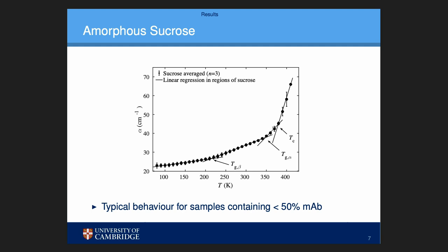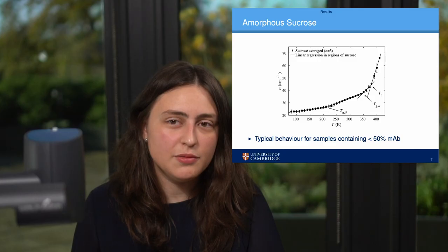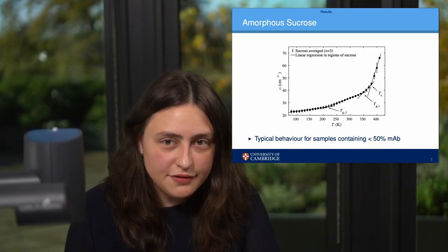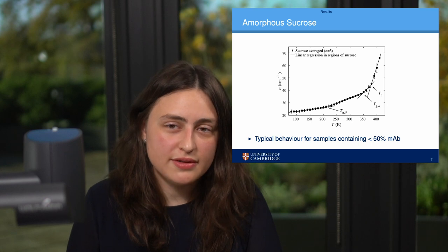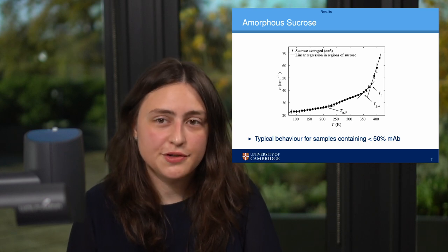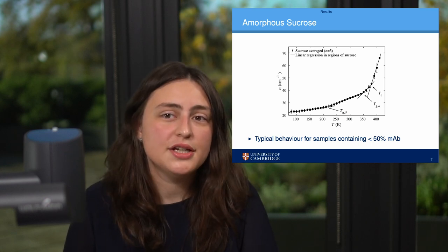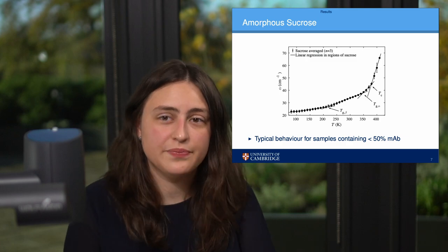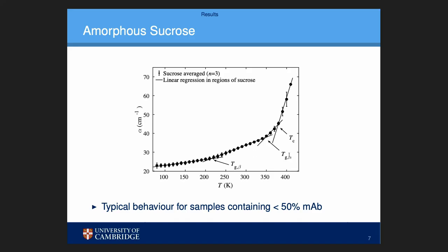That is because at that glass transition point, the mobility in the sample is increased. You have more translational and rotational motions becoming available, and changes in dihedral angles are possible. That happens again at the so-called Tg_alpha — the glass transition temperature that you can also measure with many other methods.